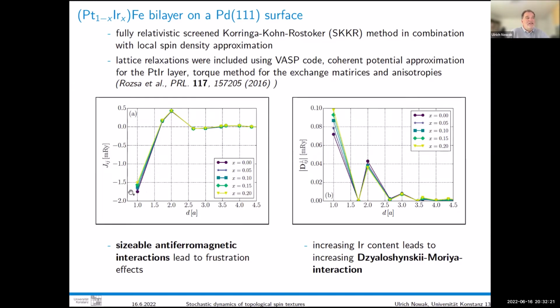So the sign convention is that the isotropic exchange is here ferromagnetic, but then there's frustration because the second and third neighbor interactions are antiferromagnetic. So it is a bit of a frustrated exchange, but also Dzyaloshinskii-Moriya interaction. And that one can be scaled with x, that is the amount of iridium in the platinum iridium layer. Now we can play games. So we can tune the Dzyaloshinskii-Moriya interaction, but at the same time we have frustrated exchange.